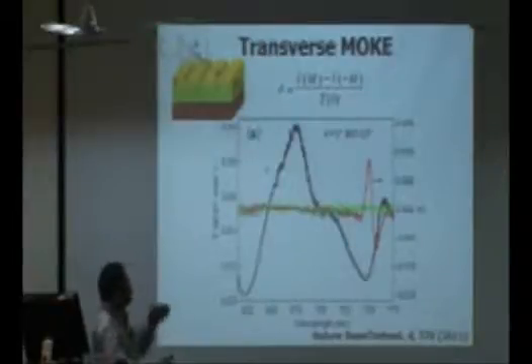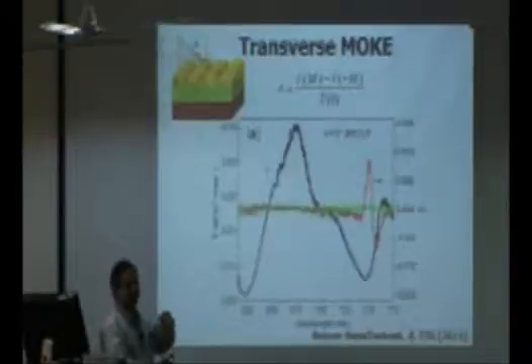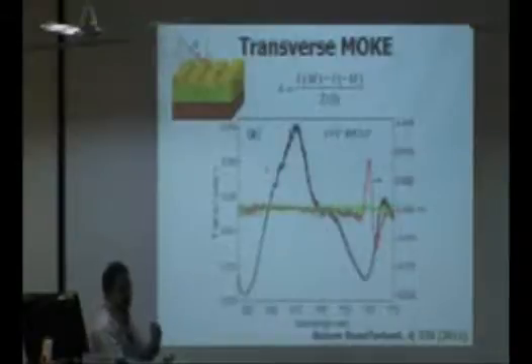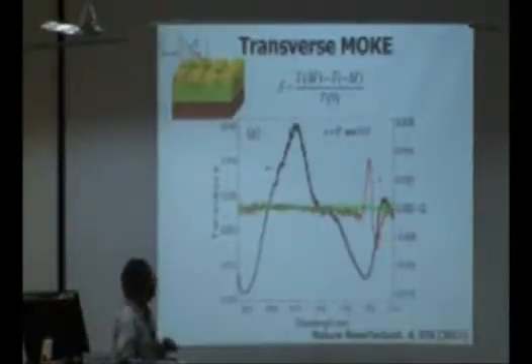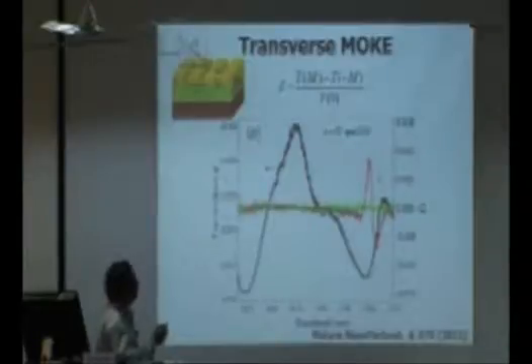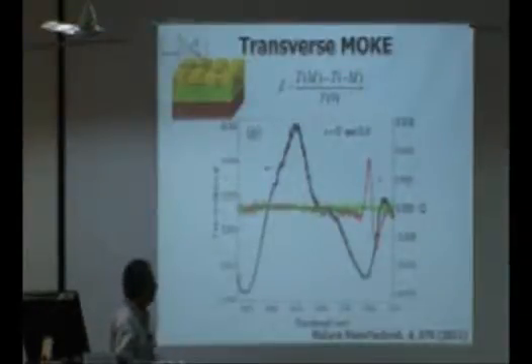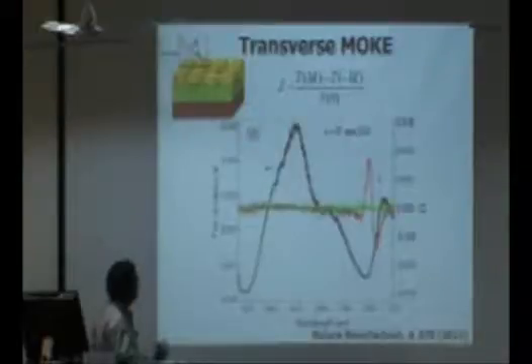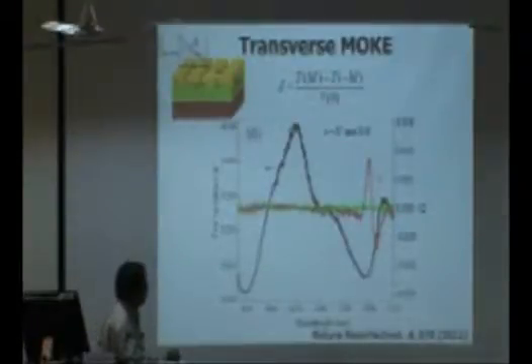What we make use of is the enhanced transmission because of the plasmon excitation, which is a surface effect, which couples to the Kerr effect, which is also a surface effect. And then we show that in transmission, we can measure this magneto-optical Kerr effect. The black curve is the measured transmission spectrum. What is interesting is that the dips correspond to plasmon absorption of the incident white light field. But these dips are pretty broad, so it's very difficult to identify where the exact plasmon resonance is.